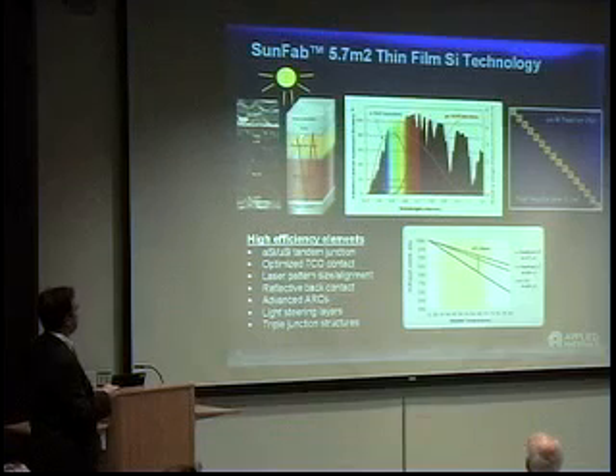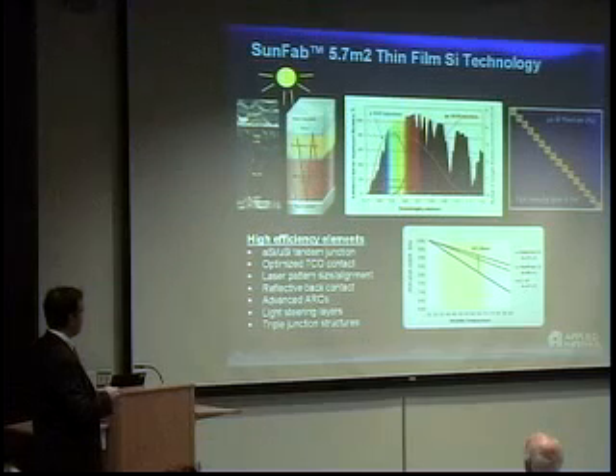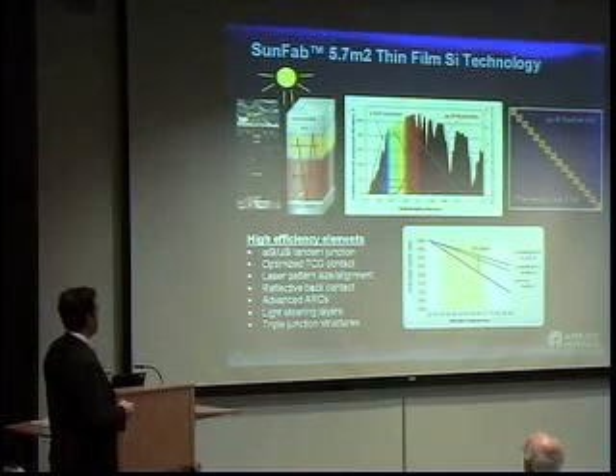We also put in light steering layers that are textured so that you try and get the light that's captured best in each of these layers focused on those layers through diffraction. You also have a mirrored layer on the back that, again, tries to keep it bouncing around in the film that it's best suited for. So you capture as much of the light with as thin a material stack as you can.